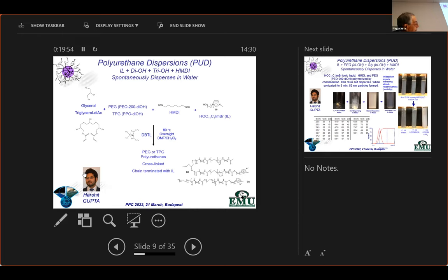We used hexamethylene diisocyanate, and then this is our ionic liquid monomer, hydroxyundecyl methyl imidazolium bromide. And let me stress that these ionic liquids with bromide and chloride counterions love water. Okay, when we get to incorporating iodide, they begin to become hydrophobic. Anyway, this is another very simple chemistry to execute.